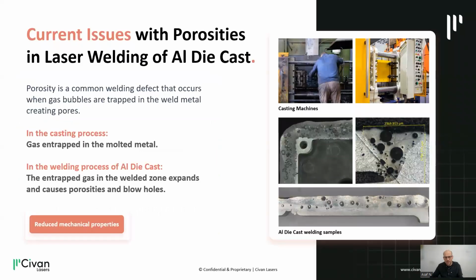We will not dive into the casting process itself, but briefly, for several reasons that depend on the dynamics of the casting process, as well as the additive used in the process, die-casted aluminum contains a rather large amount of entrapped hydrogen. In the welding process, at high temperatures, the entrapped hydrogen diffuses into the melt and upon solidification remains as a porosity defect. Additionally, the pressure inside these pores is rather high and may cause blowout that degrades the weld quality. Our solution is based on several concepts that involve degassing the melt pool by high stirring, elongation of the melt pool length and size, and if needed, a fast repair process. This results in a low porosity, high quality weld.